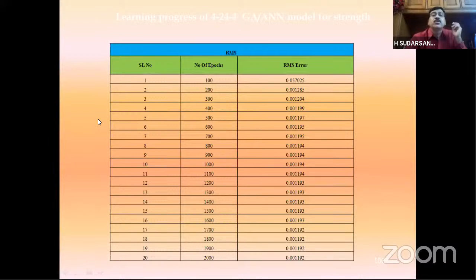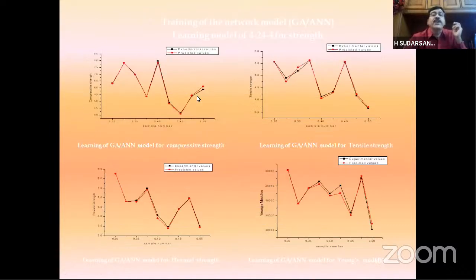This 4-24-4 network is trained with different numbers of training cycles, from 100 to 2000 cycles, and we can see the RMS error is reducing gradually. After 2000 cycles, the RMS error is 0.001, that is 0.1%, very, very less. At this stage, we think that the network training is completed. Here I am showing you the comparison between the actual value and the value predicted by the network for compressive strength. You can see the network has predicted very closely to the actual values.